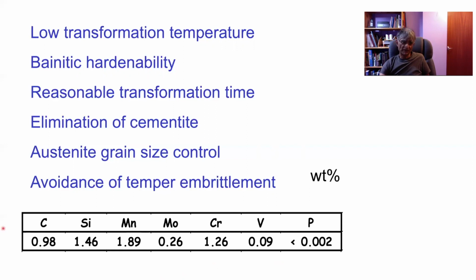Now, it's a fairly simple alloy, and we've got enough hardenability to avoid pearlite and ferrite in a large chunk of material. Reasonable transformation time. So 10 days at 200 degrees centigrade is perfectly reasonable. It's like putting the steel into a pizza oven. It's not expensive. And we've got rid of cementite. Vanadium is there to form small vanadium carbides, which help to control the austenite grain size and stop it from coarsening, and molybdenum to avoid the embrittlement.